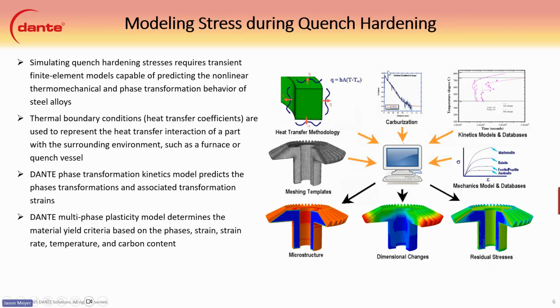So how do we model the stress during quench hardening? With DANTE, we use transient finite element models capable of predicting the nonlinear thermomechanical and phase transformation behavior in the steel alloys. You can see a lot of these yellow or orange arrows here all go into the computer model here. We use thermal boundary conditions, basically in the form of heat transfer coefficients, that we apply to surfaces to represent the heat transfer interaction of the part with the surrounding environment, such as the furnace, the quench vessel, and so on.